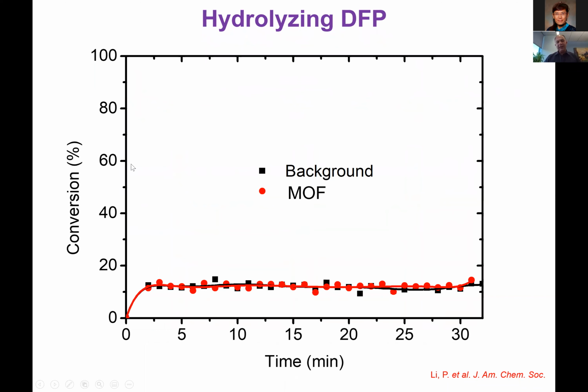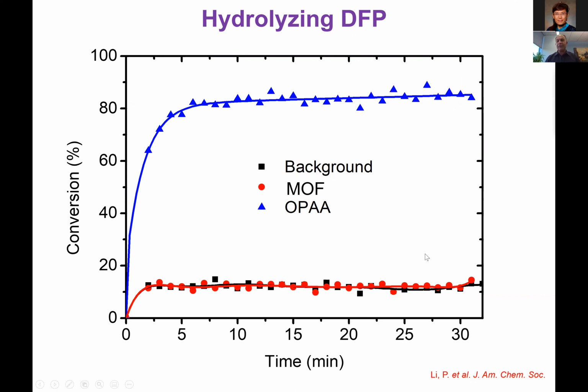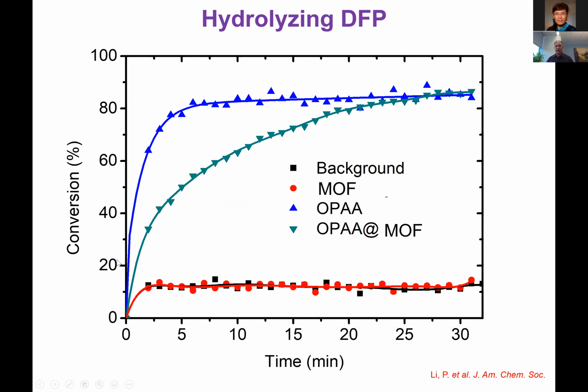Does it work well? So this is here what I'm showing you, the catalysis. This is the background. This is the free enzyme, and this is our composite. When I show this slide, I always say there is good news and bad news. If you have 30 minutes to wait, yeah, our reactivity is just as good as the free enzyme, and I will show you later that we are able to stabilize it further, but our initial rate is so much worse than the free enzyme because we have a diffusion barrier. Things have to diffuse into the channels and come out, and we have to address this, and hopefully I will show you how we address it in a couple of slides.